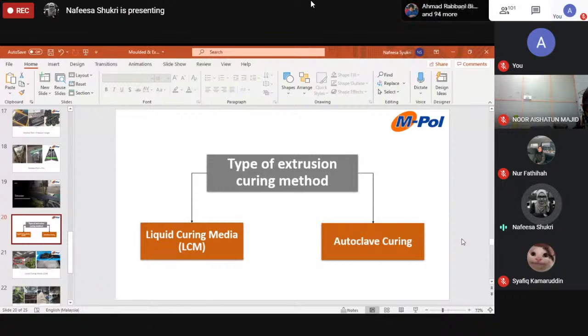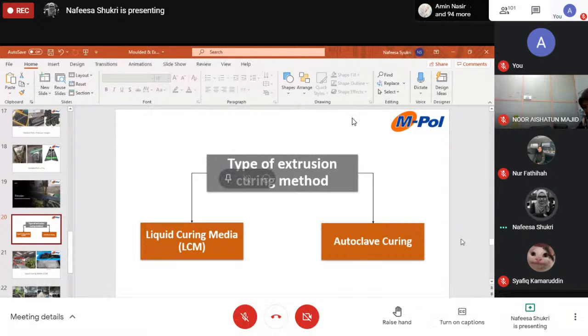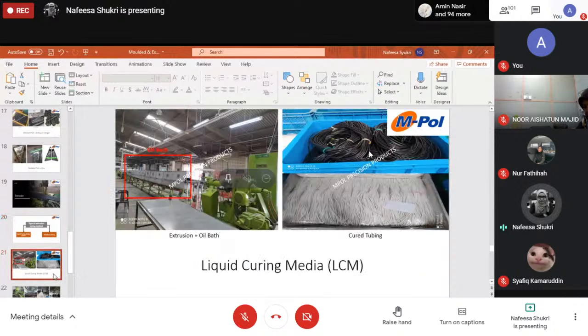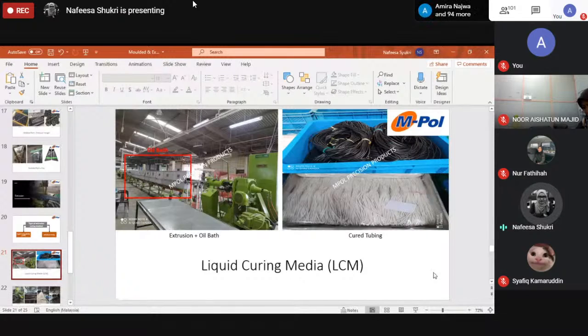So basically these curing methods depend on the size of the products, the complexity of the products, and also the thickness of the products. For liquid curing media, we extrude the thin products and also the small size of ID and OD products. For the autoclave curing method, we do various profile extrusion products, very thick extrusion products. So I will go first for the liquid curing media, which we call LCM.